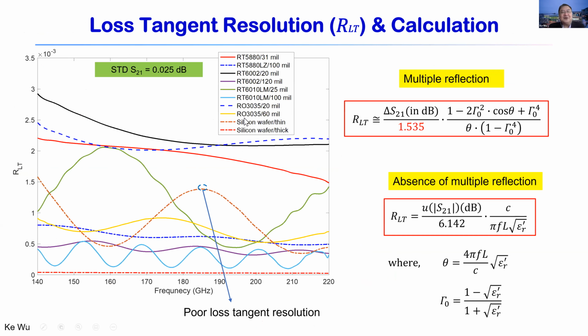So, for example, this loss tangent here for different materials, you can see that for these values, for example, there are very large ratios, and these ratios mean that if your loss tangent is smaller than these values, definitely you cannot get accurate measurement results, because the loss tangent resolution cannot be satisfied. You can only measure the high loss materials larger than these values. So these values come from the calculations.